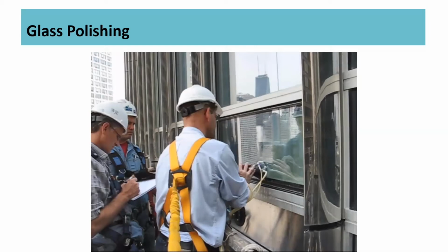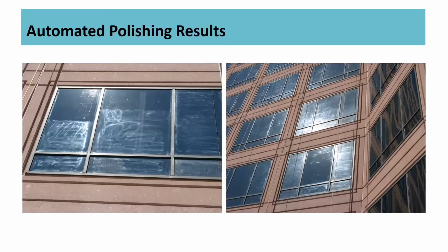When they're done, the device is pulled off the glass. There's a very small drip of cerium oxide slurry that's easily wiped up. And this is a project I showed earlier where the damage was done using a proprietary cleaning compound. And we used that automated procedure in these boxed in areas.